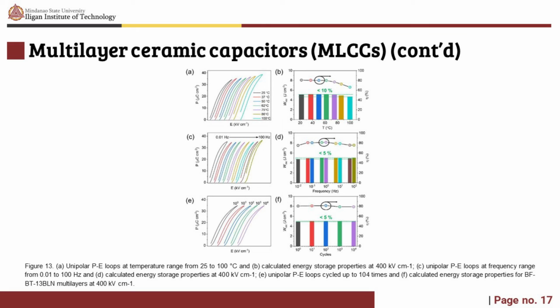BT-BF-13BLN multilayers are rare earth-free with a low sintering temperature of 890 degrees Celsius, providing an opportunity for sustainable manufacturing and indicating potential compatibility with silver-palladium internal electrodes. Multilayers with x equal to 0.13 therefore have the potential to replace the lead-based system for pulsed power applications.